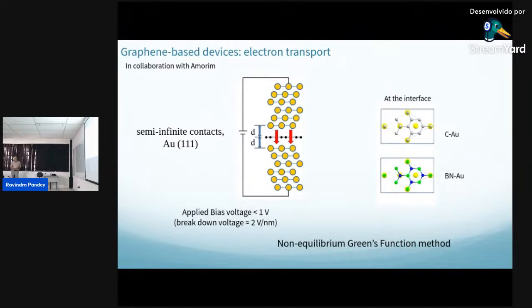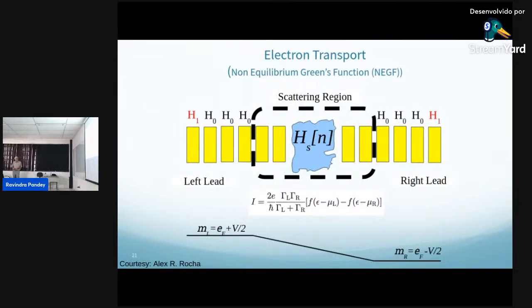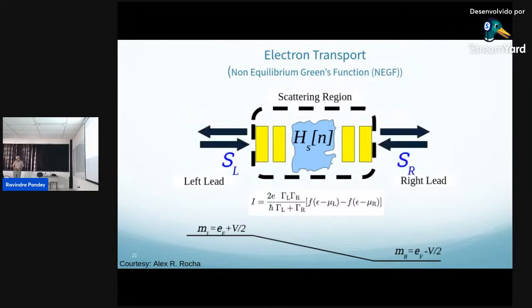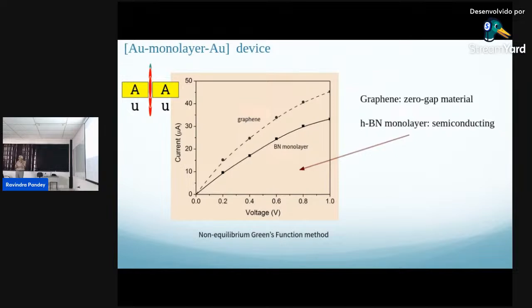And this is the technique we'll be using, a non-equilibrium Green's function. You've seen this again, coming from one of our earlier collaborators, Roshan, with whom Rodrigo worked. So we are looking at this quantum region, and then we have the left and right contacts, and we have the so-called contact functions, gamma L and gamma R, which include their contributions. From here we have the transmission function, and from there we can derive the current versus voltage characteristics. So you can see that from materials we have gone to a device, and we can give this IV curve to experiment. You can see how good or how bad the material is. That's the connection with the industry or the experimental physicists.